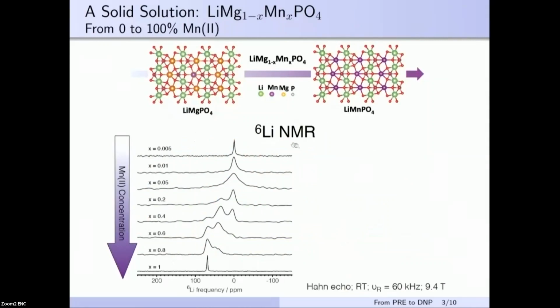So here I'm showing you the lithium-6 NMR spectrum for various concentrations. What we observe is that at the low concentration regime, we have a single peak as expected from the crystal structure, which is quite narrow. As we increase the content of manganese, this peak becomes broader and broader. But then we reach a point where it starts becoming sharper again, and at this point we're able to observe multiple sites. These multiple sites are due to differential Fermi contact shifts, but I don't want to go into that part of the story today. Instead, I want to show you something else.